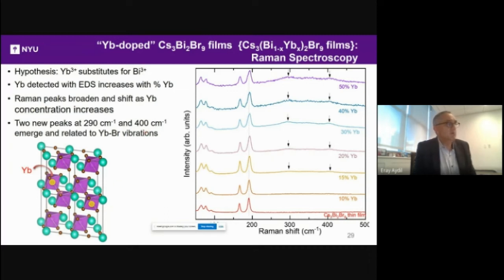So we think that the ytterbium 3+ is indeed going into the bismuth 3+ site, and the size of the ion is also such that it can do that. Moreover, it's difficult to explain putting in 50% ytterbium and not seeing any other phases appear. It has to go someplace without disturbing the overall structure.